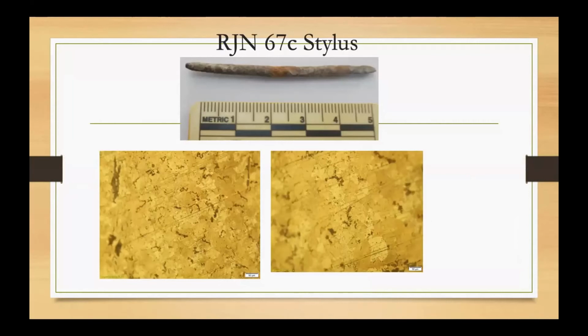Then we have a stylus. Here, the stylus, as you can see, is intact. But when I cut it and went inside, the sample was extremely corroded, and I could not get a very good microscopy done. But the granular structure was visible, and we could understand it's a pearlitic formation. But doing a TEM on this would have been better, because a TEM requires a very small area and gives you a very high magnified image, but that is not available to us at the present moment here.